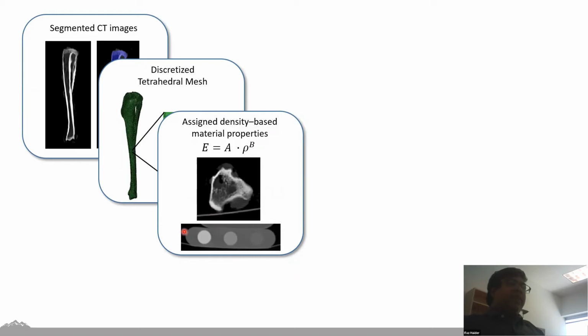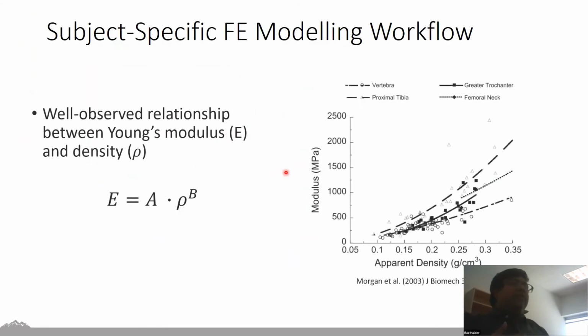And in all of our scans, we had an object that was called a calibration phantom. This is basically just a region with known mineral densities at 3 of its sites. And so by measuring the calibration phantom, we're able to quantitatively relate the CT measurement, or the brightness of this image as I'm showing it here, to an actual bone density value. And this bone density value forms the basis for how we might estimate something like the bone's Young's modulus. Now, in the literature, there's a very well-established relationship between bone density and Young's modulus. And it's usually described with an equation like this, where the Young's modulus is equal to some constant A times the density raised to some power B. The tricky part is figuring out exactly what A or B should be for a given set of models.